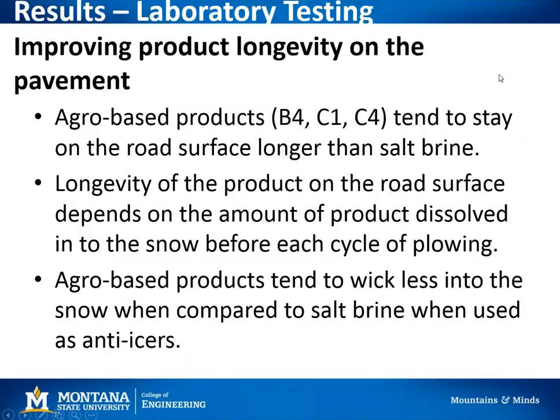So to summarize, for the agro-based products that were tested, and these are just the B4, C1, and C4 products, they tend to stay on the road surface longer than salt brine alone, and the longevity of the products on the road surface depends on the amount of product that is dissolved into the snow or wicked up into the snow before each plowing cycle. And for agro-based products, they tend to wick less into the snow when compared to salt brine, and this may have to do with the viscosity of these products.